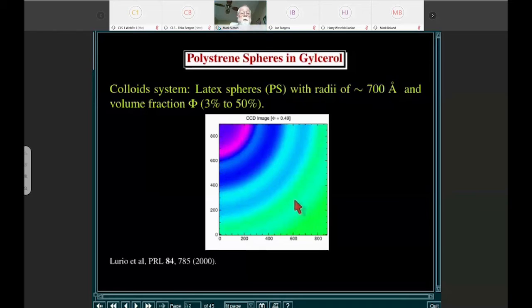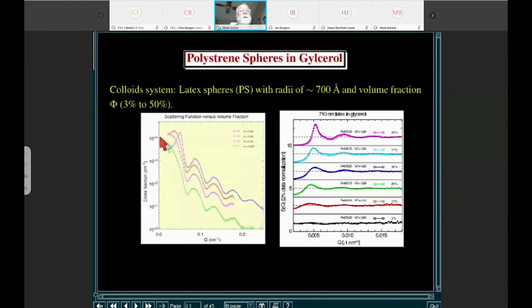So there you can't really quite see the speckle pattern, because the other way to get rid of the speckle pattern is to average over many, many fluctuations. And so this is the scattering averaged over the full sequence of data that we took, including many, many fluctuations, and there's the reference. So if we were to look at the circular average of that scattering, and here we see it for 4 different concentrations, you would get the normal small angle coherent scattering. So we have very nice spheres, so you can see the Airy fringes from the spheres, and the green curve, which is for 3% volume fraction, is basically N times the scattering of each of the particles.